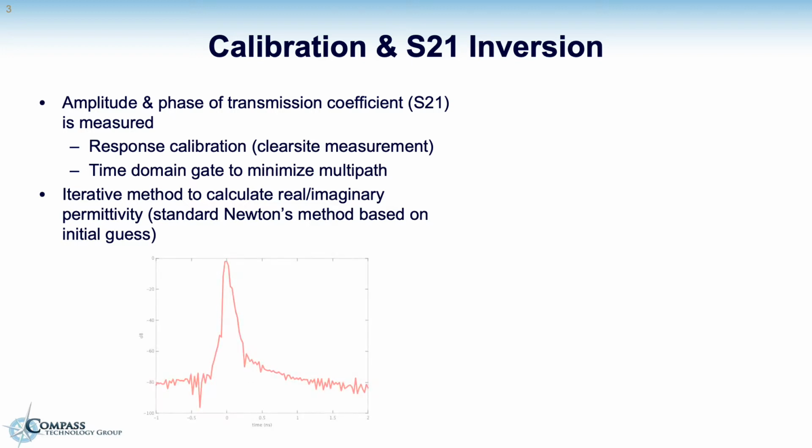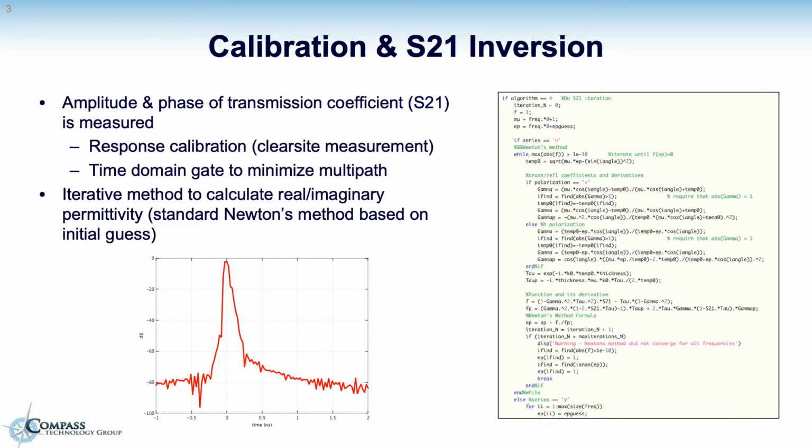And then we combine that with time domain gating. And the key about time domain gating is that it helps us to eliminate the multipath errors, from reflections at different junctions, the horn antenna, the lens, the ported network analyzer, that would otherwise be taken care of by a more advanced calibration method. So in that case, we take lots of data over a range of frequencies, and then we can use Fourier transform techniques to transform into time domain, put windows around the data that we know is relevant, and zero out the non-relevant reflections, and then transform back into frequency domain.